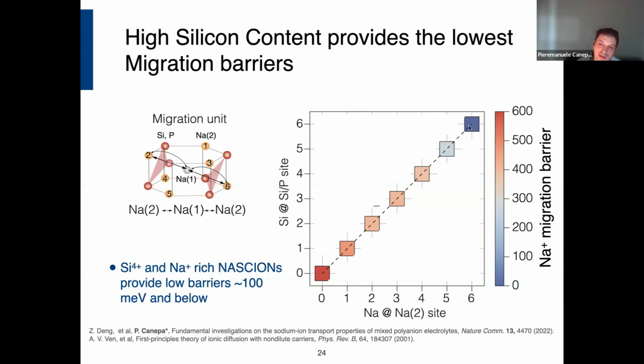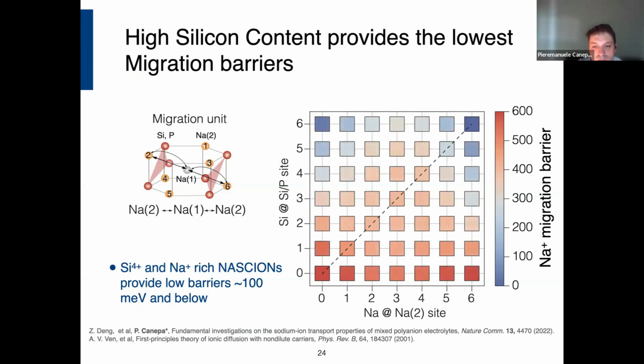And when we go to very high silicon content, meaning 6 here, and very little amount of vacancy, the barrier becomes very, very low. And of course, we can now use our model. These are computed barriers, but there is a model in between, a cluster expansion, and we can compute all the barriers at different compositions of sodium and vacancy on the sodium 2 sites, and silicon, phosphorus. You can see you have a variety of situations. We use this model, which is fast to compute now. It doesn't rely on first principles calculations anymore. This model can predict the migration barrier of sodium at any composition in terms of silicate and phosphate in this unit, and sodium and vacancy.